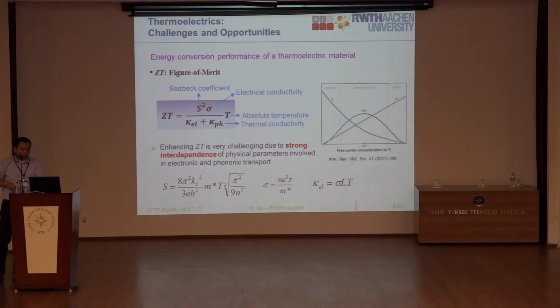So this is a very typical figure. This shows that the Seebeck coefficient and the electrical conductivity, as a function of free carrier concentration, have opposite trends. So it shows that at the optimal free carrier concentration, you can realize this S squared sigma to be the maximum, so that you can maximize this power factor. But of course, in the meantime, you also have to consider the effect of the free carrier concentration on the phonon transport. If you consider everything together, the whole study becomes very, very complicated.